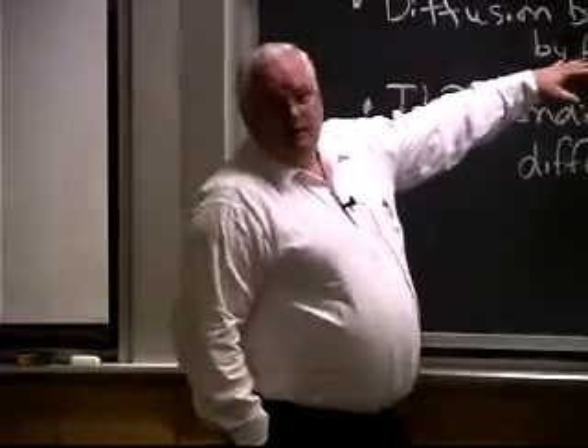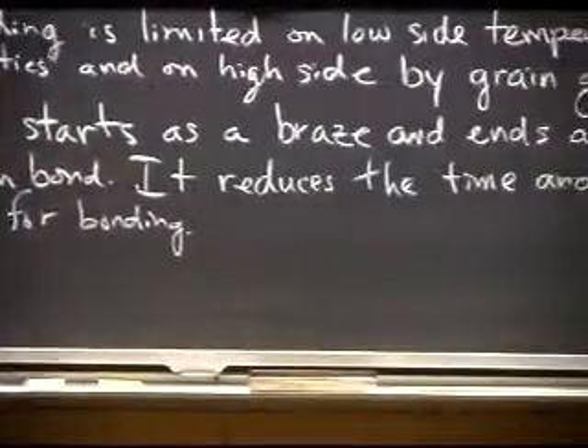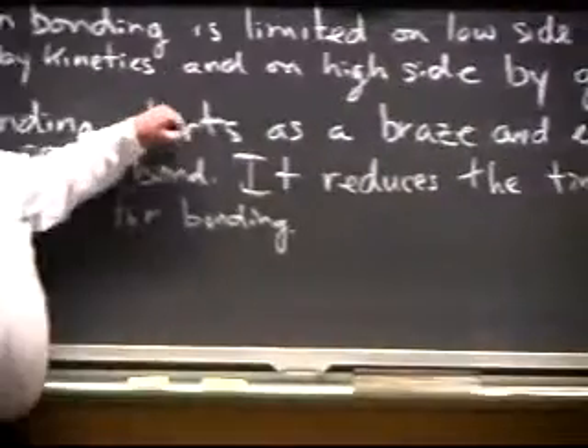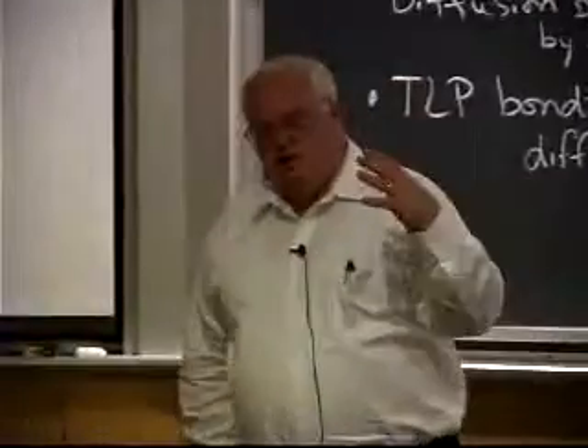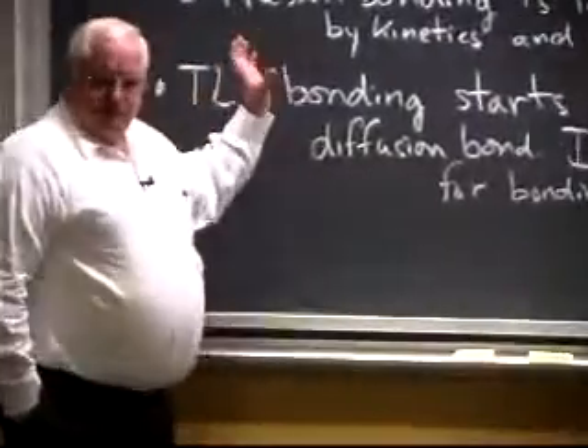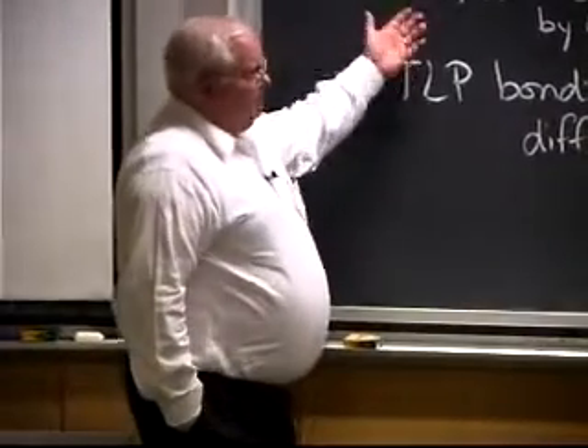So aside from hacks and things like that, we were talking about diffusion bonding, and it's limited on the low side temperature by the kinetics. It's just going to take too long in the furnace. You can get great bonds, but it'll take you forever to do it because diffusion is slow at low temperatures. It's limited on the high side by grain growth. You'll get recrystallization across the interface, and you'll trap pores, and the pores are going to weaken the interface where you made your bond. So you're limited by this kind of 6/10 to 8/10 of the absolute melting point as an effective temperature to do it.